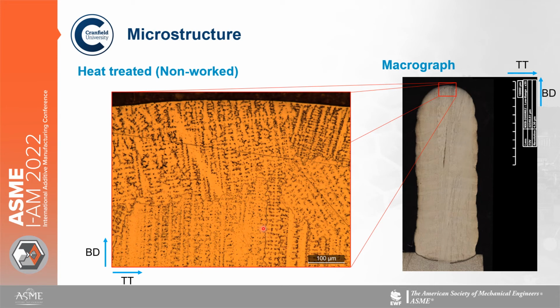And if we zoom in a bit more, we start to see our grain boundaries here. And again, we see this dendritic structure with secondary dendrite arms. Again, the very last layer, they're orientated slightly differently than the rest of the sample. As you can see further down, dendrites tend to be orientated in the build direction.